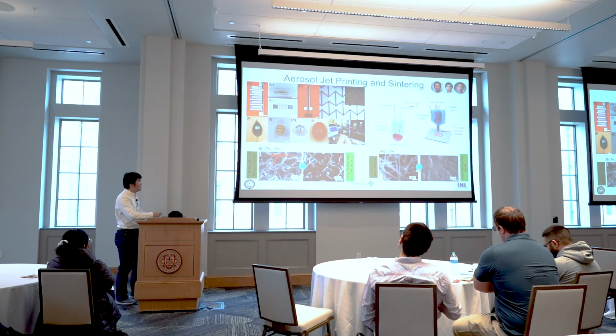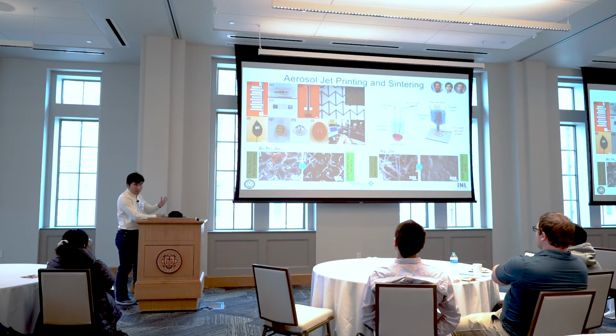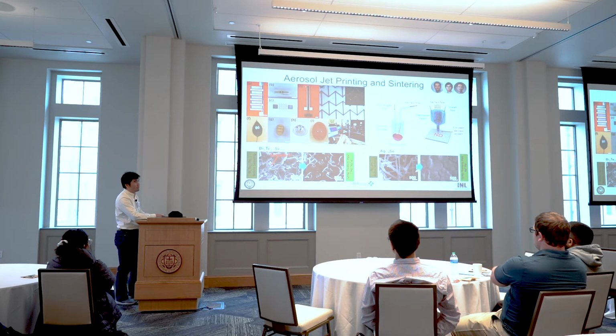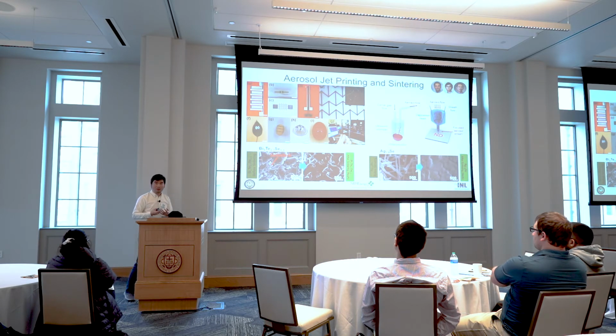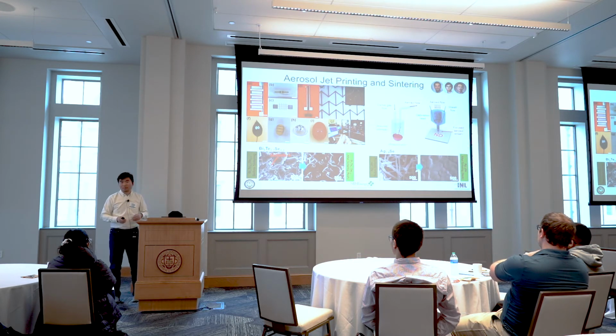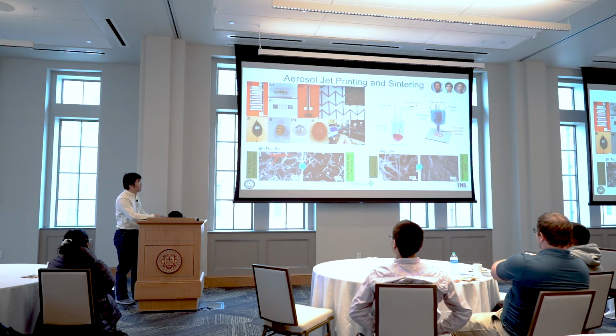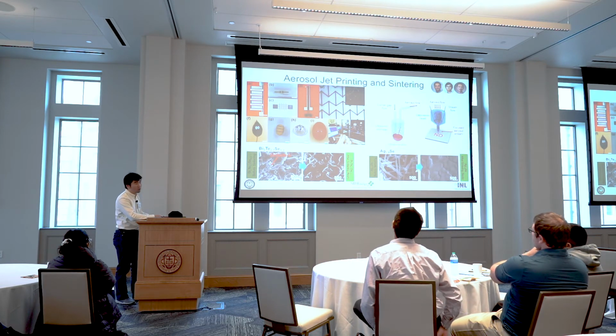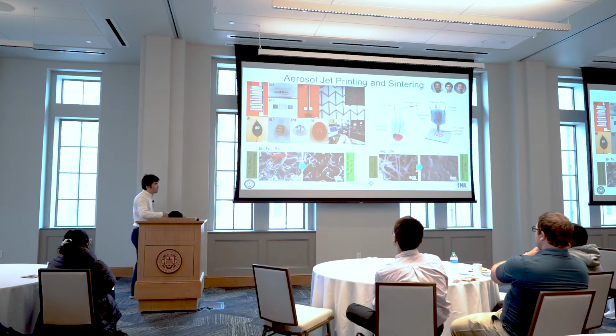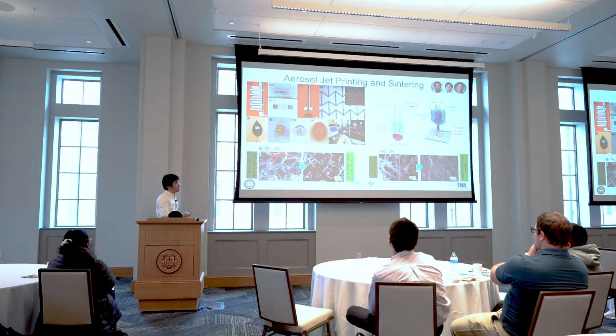So here I give you two examples. One is bismuth telluride based, which is the state-of-the-art material. The other is the silver selenide based material. So on the left, it's as-printed material, and on the right, it's after sintering. So usually, how people do sintering is put it in the oven, bake it, like you bake a cake, for a few hours, and then hopefully the solvent would evaporate, and the grains will grow, and then they merge. Then obviously you can think this is much better for transport than this one, right? Because it has a lot of interfaces. Okay? So sintering is a key step to improve the efficiency of your printed material.